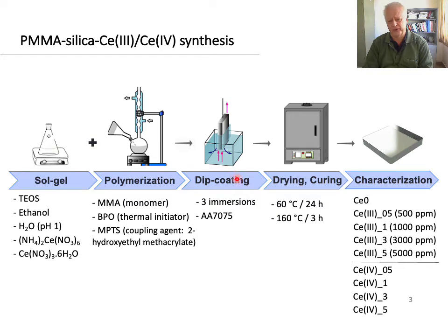The homogeneous solution was then used to deposit PMMA silica coating by immersion on the aluminum 7075 alloy. The samples were then dried, films but also freestanding samples, at 60 degrees C during 24 hours and then cured at 160 degrees C for 3 hours. Following this procedure, 2 sets of samples were obtained containing between 500 and 5000 ppm of both cerium precursors. They were labeled as cerium-three 05 to cerium-three 5 and then cerium-4 05 to cerium-4 5, including the PMMA reference referred to as cerium 0.